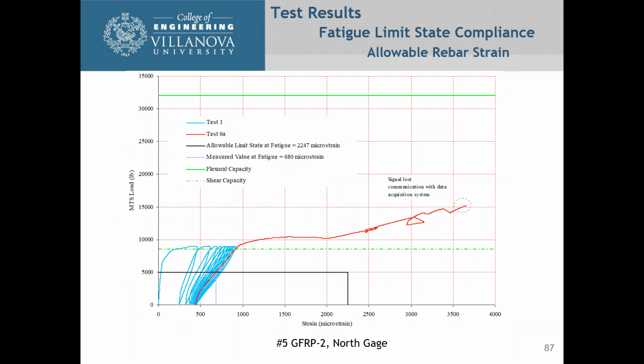Here's the other number 5 sample that we had, and you can see again that our measured microstrain was 680, and the allowable was 2247. Again, you can see as we tried to load this thing out, we lost signal on the strain gauge.